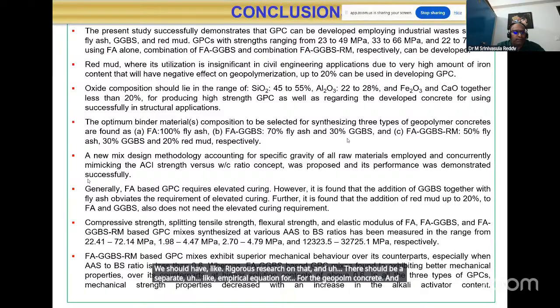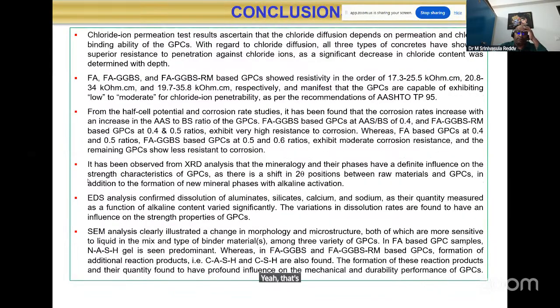And finally, durability wise, this is the best compared to normal concrete from an acid resistance point of view, alkalinity, pH point of view, corrosion point of view, but not for all the ratios. You can say up to 0.4, 0.5, 0.6, more or less we use that ratio only. We don't go to 0.7, 0.8 generally for structural concrete. Maybe for non-structural purposes we can go for 0.8 also, but more or less 0.4 to 0.6 is the generally used ratio. So for all this we can say this is the best compared to normal concrete. Yeah, that's all from me.